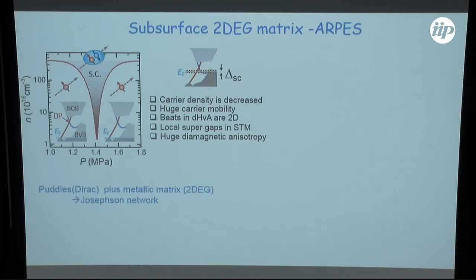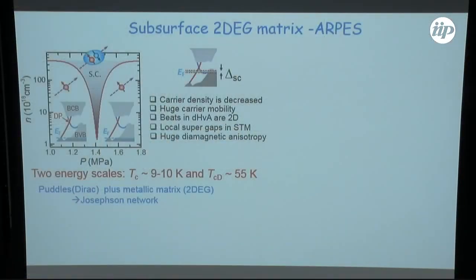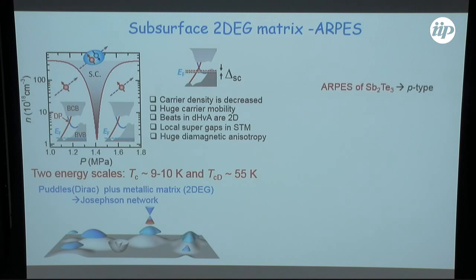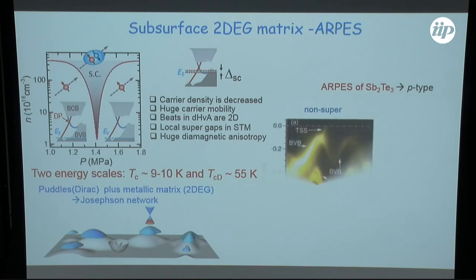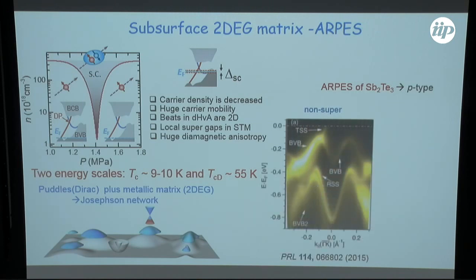So basically, I'm trying to argue that what we have in this system, it's kind of a mess. Okay, it's a puddle Dirac system plus a metallic matrix, which is a 2DEG. And so we have some sort of a Josephson network with two energy scales, one around 10 Kelvin and one around 50, 60 Kelvin. And the question is, of course, what this system is and whether indeed there is some indication of topological superconductivity here. Now, first thing, of course, was to check whether we still have Dirac states.